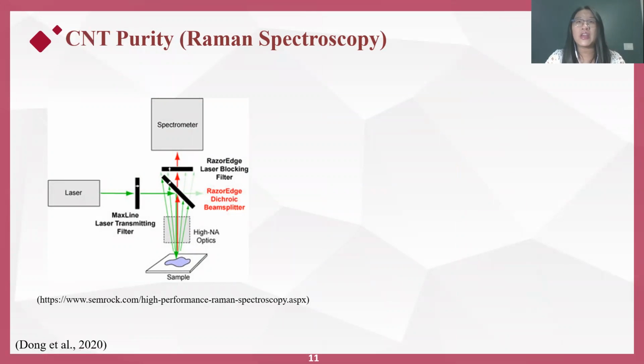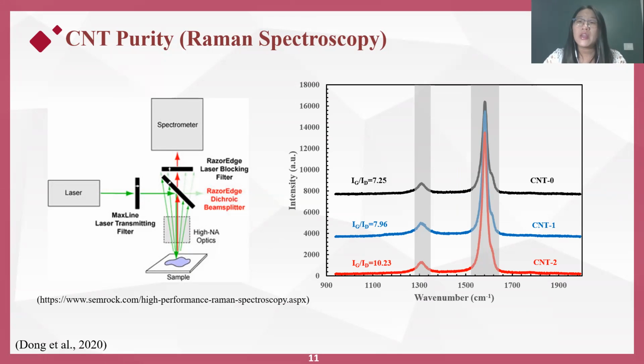Raman spectroscopy is a non-destructive chemical analysis technique based on the interaction of laser and the chemical bonds within the sample. So for carbon materials, our focus is normally on the sp2 and sp3 hybridized carbon. At approximately 1580 per centimeter, the G band is characteristic of ordered graphitic structure, and it corresponds to the carbon atoms vibration along the CNT axis. And the disorder-induced D band at around 1310 per centimeter indicates the relative amount of defective impurities or other symmetry-breaking defects. Especially in our case, we're talking about the amorphous carbon. Therefore, we use the intensity ratio of these two bands, IG over ID, as a direct measure of CNT quality.